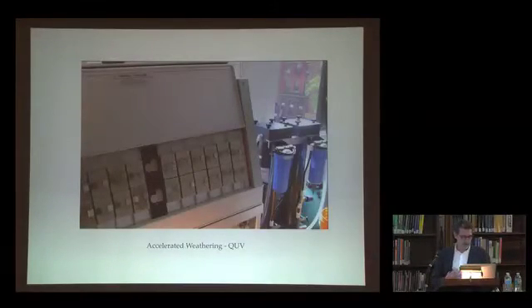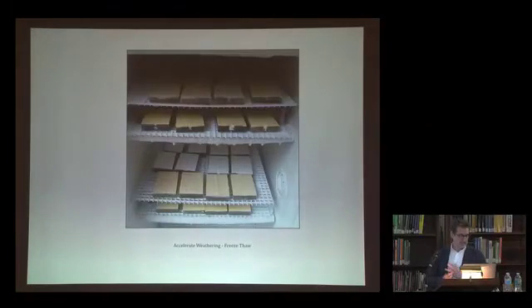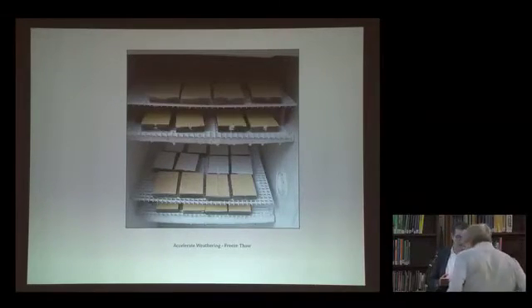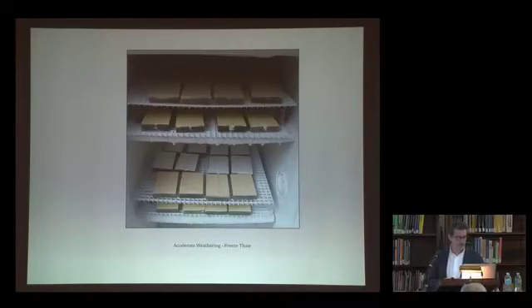A QUV weatherometer was used to expose test panels to accelerated conditions of ultraviolet light, condensation, and associated heat, and thermal shock as a result of applying cooled water in a spray to those samples. The first round of tests exposed samples to 1,500 hours of exposure, and samples were evaluated every 500 hours. The cycle for freeze-thaw testing was 16 hours thawing in 22 degrees centigrade water, followed by 8 hours of freezing in minus 22 degrees centigrade air. Changes in test panel appearance were noted after each cycle and were photographed approximately every 6th cycle. The tests were run for 30 cycles.